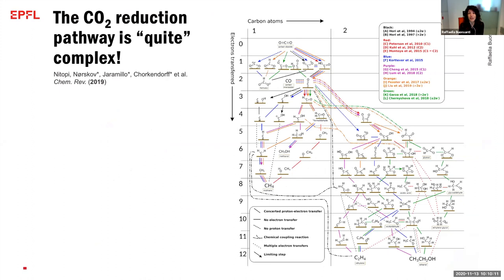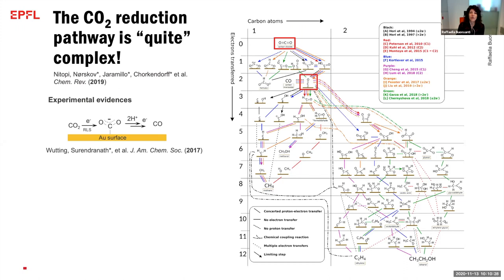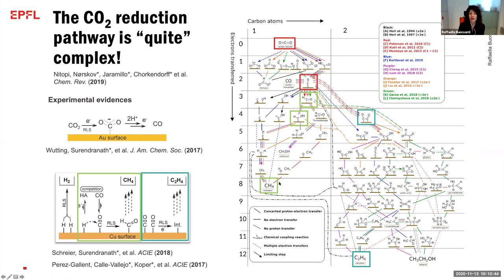Why don't we have a catalyst? We don't have a catalyst because the CO2 conversion pathway is extremely complicated, and theorists and experimentalists are still working together to try to figure out what is the mechanism of this conversion. Some initial results are coming out. If we focus on the simple first step, which is the conversion of CO2 to CO, experimental evidence suggests that the rate limiting step of the reaction is the first electron transfer, which leads to the formation of CO. And if we then focus on CH4 or ethylene, the rate limiting step for the formation of methane is the formation of this CHO intermediate. Instead, to produce ethylene, we need to have C-C coupling.